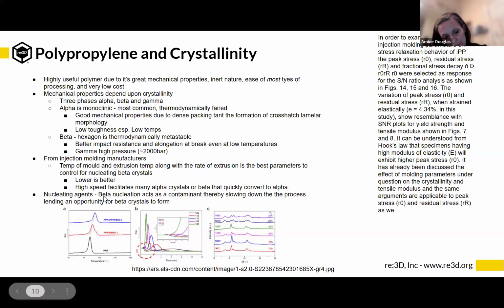I've investigated nucleating agents as well. But the problem is that you would have to pre-mix these and you'd have to get really good exfoliation. And by exfoliation, I just mean really well mixed. Yeah, a homogeneous mixture. And actually, you want to intercalate it. You want it to get inside the polymer chains really well, interacting with each polymer chain. You want to separate the crystalline areas. And that will decrease the time for the crystals to form.